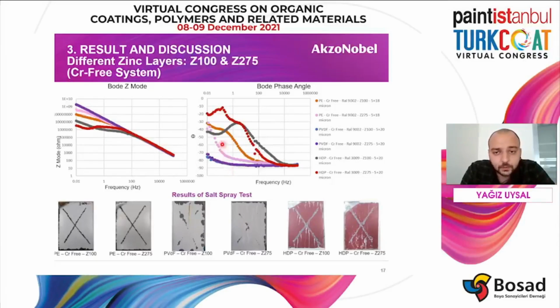If you look at the phase angle diagram, the pink one, the 275 gram zinc layer, reaches 90 degrees at the lower frequencies and has much more linear behavior. And if we compare the accelerated test results, all the samples that contain a zinc amount of 275 have better results.